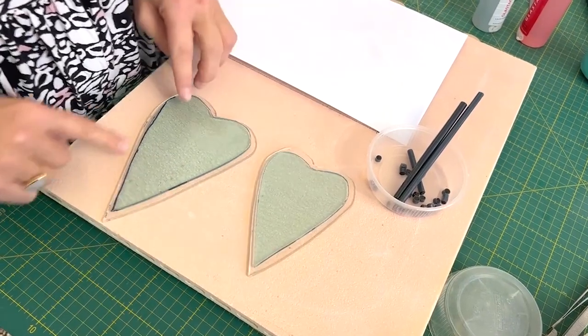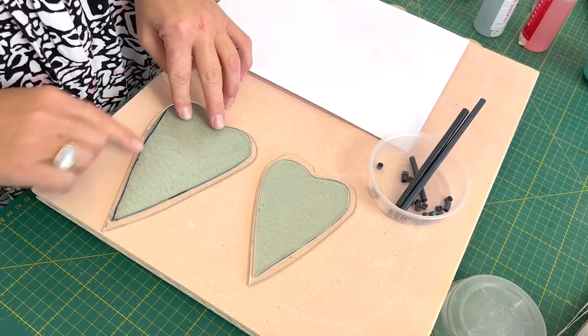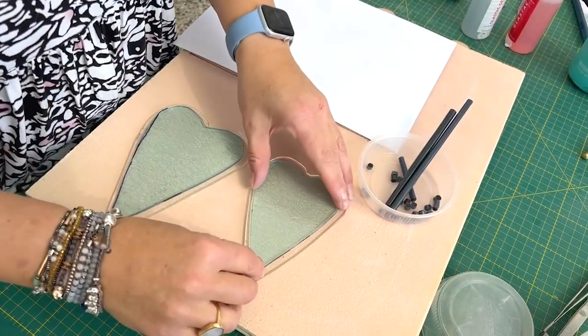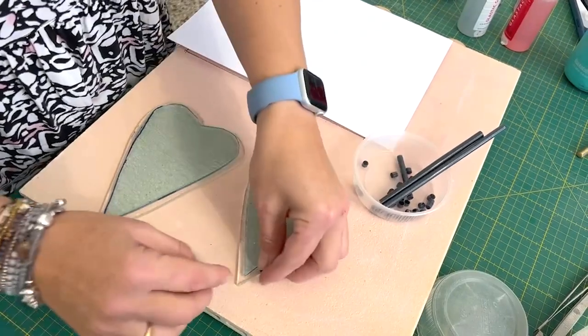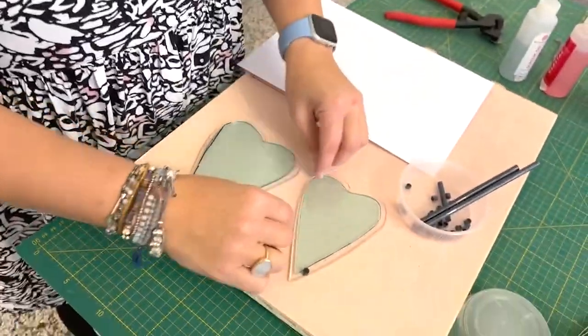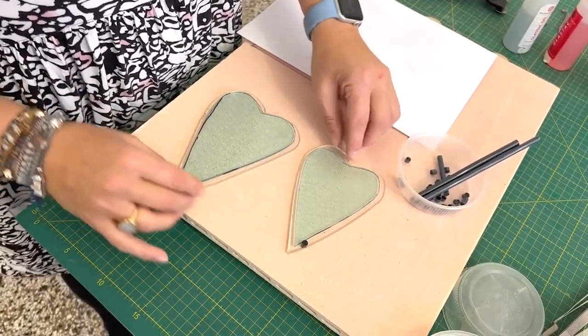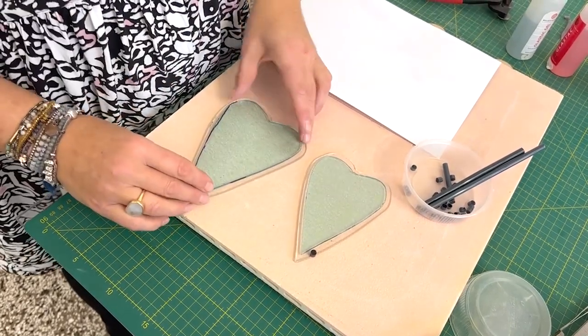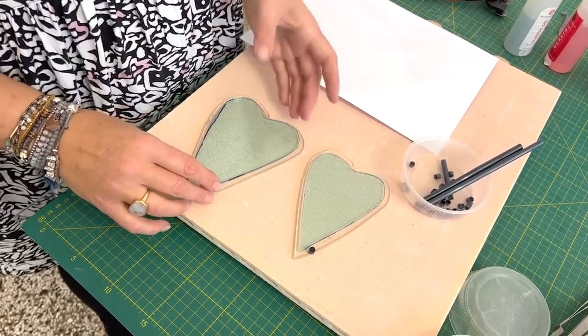You can see I've cut these to size. I need to give this glass a clean — always clean your glass, and if it's still got sharpie on it that's probably not a good idea. I now want to make a border around the edge, so I'm going to dam this. I'm cutting pieces of fibre paper about 5–6 millimetres thick because you want it slightly lower than 6 millimetres. I'll put it around here with little dams all the way around to hold this, because if I fire it now it'll just lose shape, become a blob, and won't really look like a heart anymore.